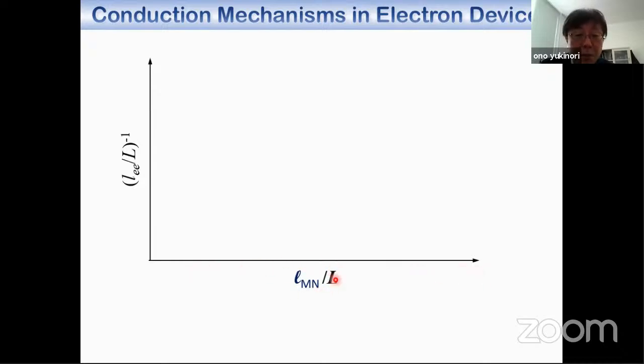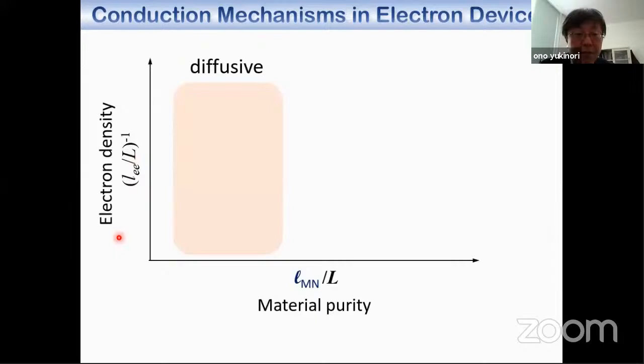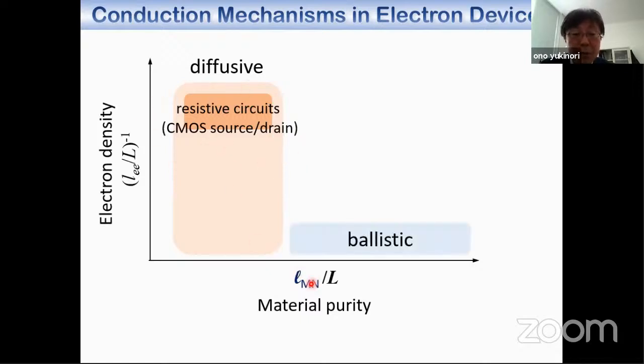Here, this axis corresponds to the momentum non-conserving scattering length scaled by the device size. This is a good measure of the material purity. Here, we take the inverse of the LEE scaled by L, which roughly corresponds to the electron density. And when LMN is quite small, irrespective of the electron density, we observe diffusive transport of electrons. And the resistive circuits, including CMOS source and drain, correspond to this area. And also, when the material is quite pure or the device is highly scaled, and also the electron density is quite small, we observe ballistic transport.